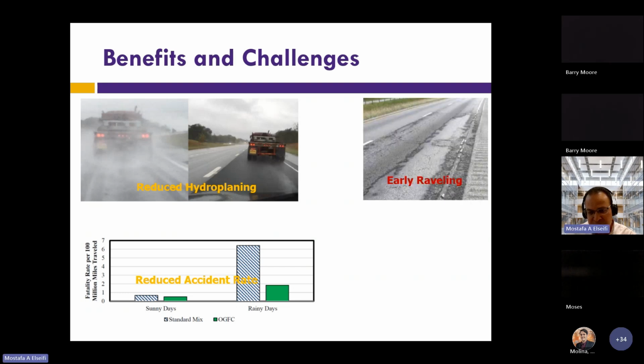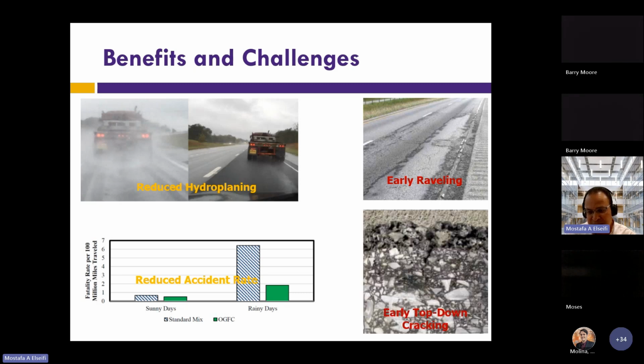In terms of durability, these are examples of raveling of the mix. It's usually constructed with a very thin thickness, which again makes it very susceptible to raveling. We have also seen in the literature early top-down cracking from this mix. So it has a lot of performance issues, and we cannot really argue about that.